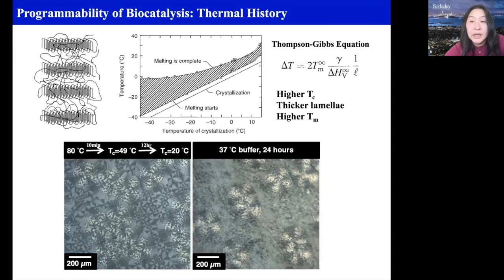And then for those of you who are familiar with polymer crystallization, polymer melting temperature always depends on when you crystallize it. So there is this inherent connection between the Tc and Tm. And then you can go with the Gibbs-Thomson equation to look at how that traces back to the structure. So basically what it says is, if you increase the crystallization temperature, the lamellar thickness gets increased, and it's going to take the enzyme a lot more effort to drag that polymer chain out of the crystalline domain. So you can also really control the degradation rate or degradation latency by the post-thermal treatment.